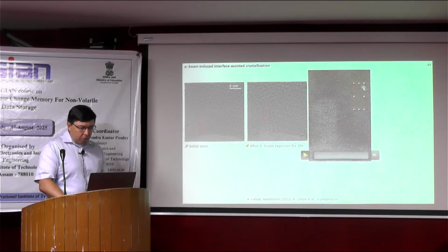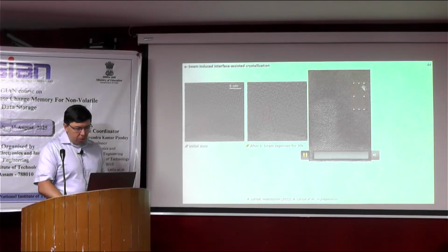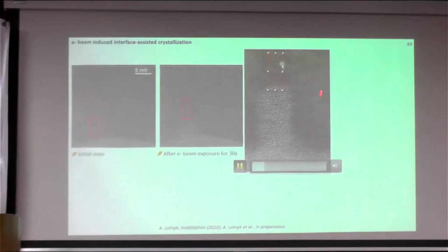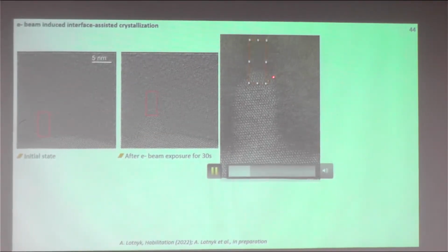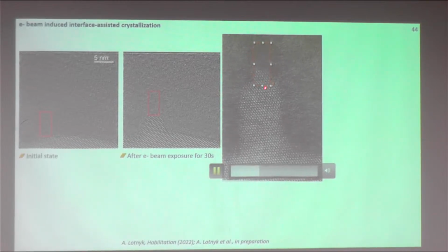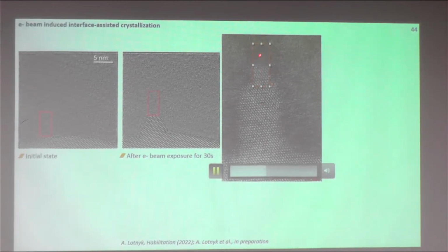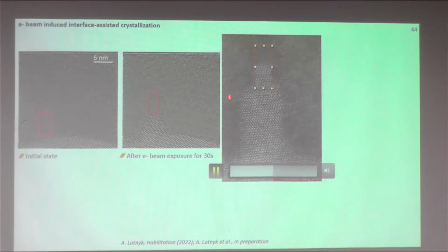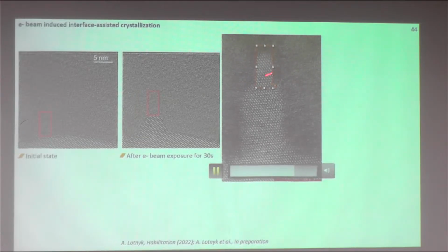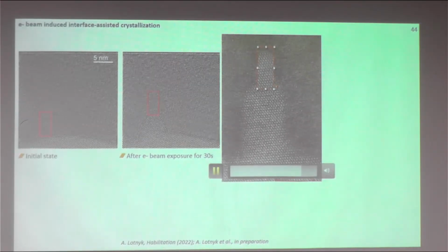We can also look at this in situ. So if you just created a nanowire of this size, then I can show that this is true. This is the real image, you scan here, nothing happens. And if you irradiate the area of these nanowires, then it starts to grow directly without any incubation time. You see nicely epitaxial growth of this nanowire.